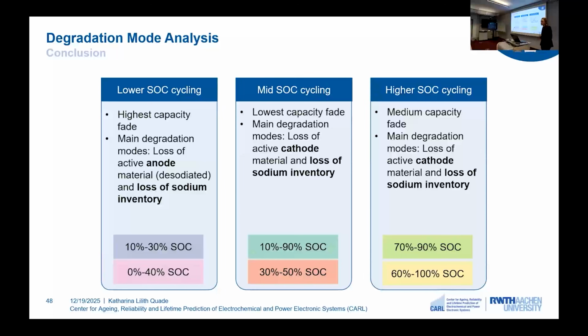For the lower SOC cycling condition, where we have the highest capacity fade, we identify as a main degradation mode loss of active anode material in the desodiated state, and we also have indications that loss of sodium inventory is happening. And for the mid-SOC cycling condition, where we have the lowest capacity fade, we identify as a main degradation mode loss of active cathode material, and the same thing for higher SOC cycling, where for both categories we also have indications that loss of sodium inventory is happening. However, the question still remains, why do we have such a high capacity fade, compared to the other cells, for the lower SOC cycling condition?